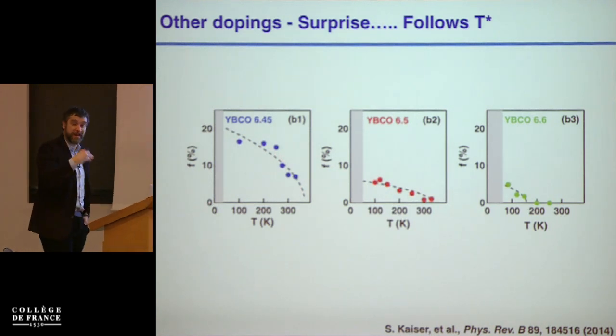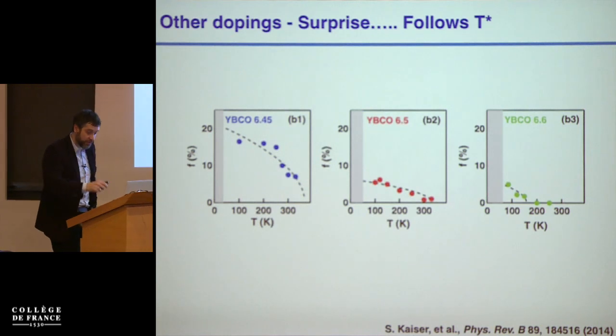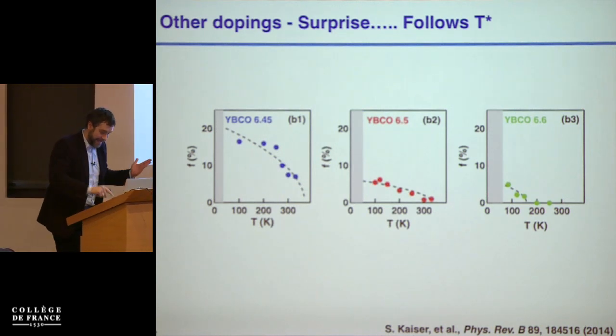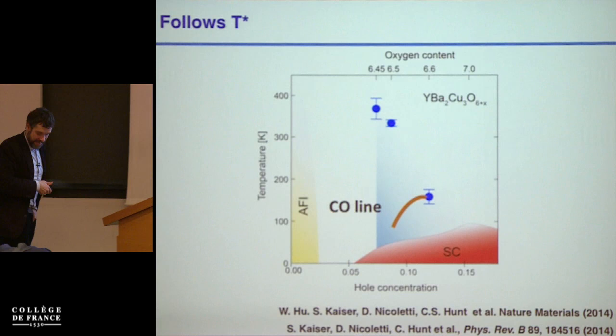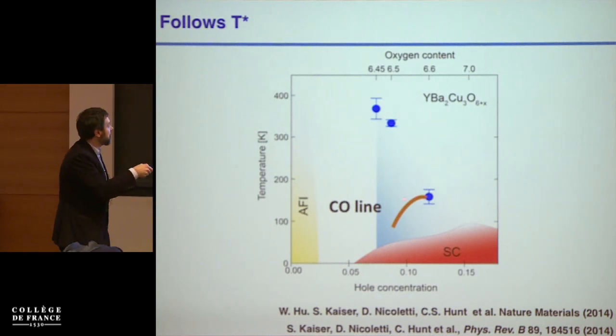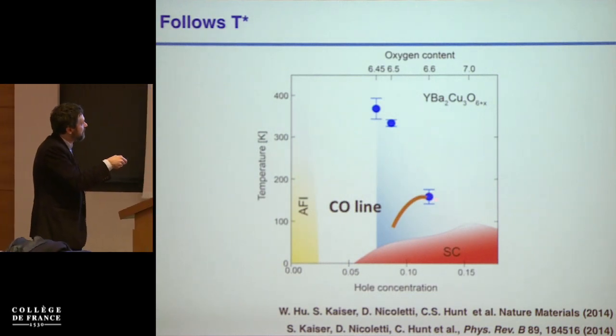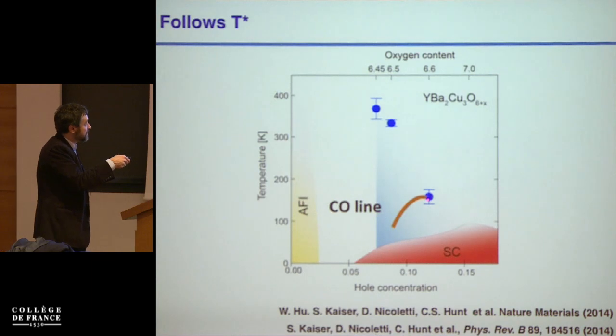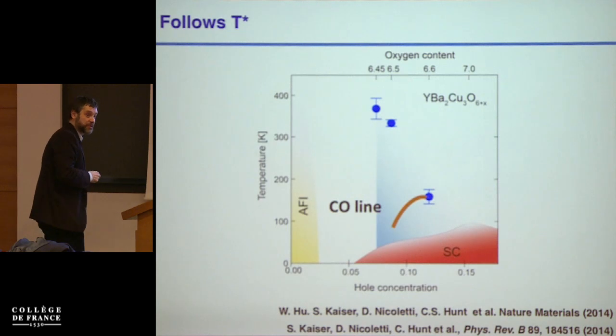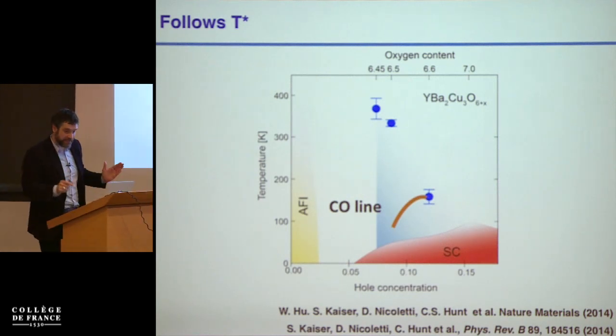This is what made these experiments extremely controversial, but nevertheless compelling and exciting. This is the YBCO 6.6 where we observed an effect that disappeared at the charge order line. Whereas when you go underdoped, although the charge order line goes here, you observe this effect all the way to much higher temperatures. So it's not really clear what's going on.